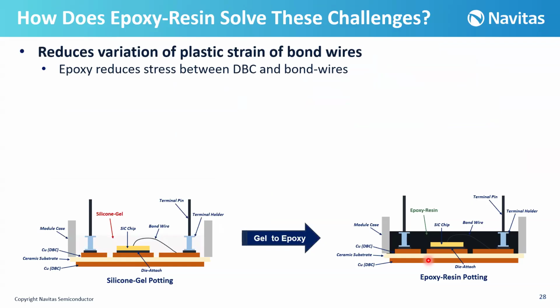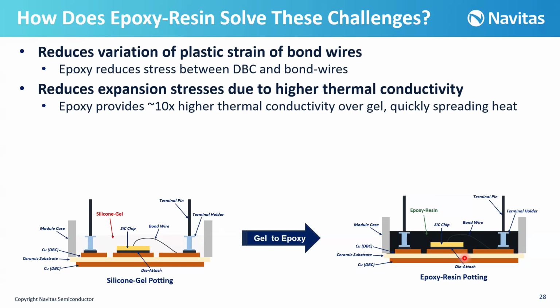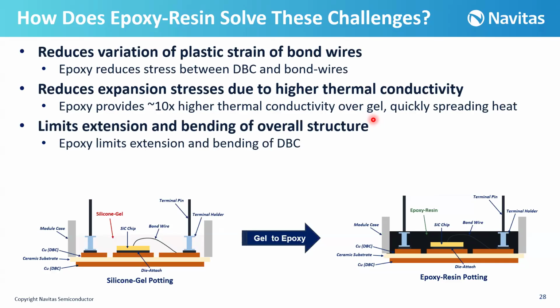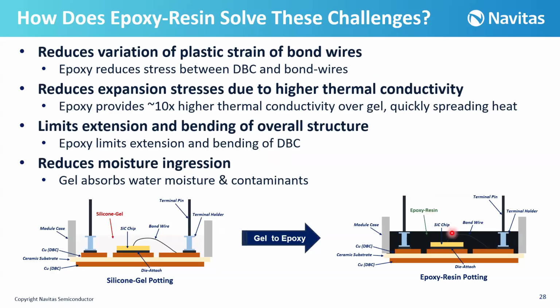How does this epoxy resin help us to improve the reliability? First of all, it reduces variation of plastic strain of bond wires. The epoxy reduces the strain between the DBC here and the bond wires. The second one is it reduces expansion stress due to higher thermal conductivity. This epoxy resin has about 10 times higher thermal conductivity than gel. So obviously we have quickly spreading heat. Then we have limited extension and bending of the overall structure. Epoxy limits extension and bending of the DBC. And finally, this epoxy resin can prevent moisture penetration into our module, but silicone gel can absorb water, moisture, and contaminants.